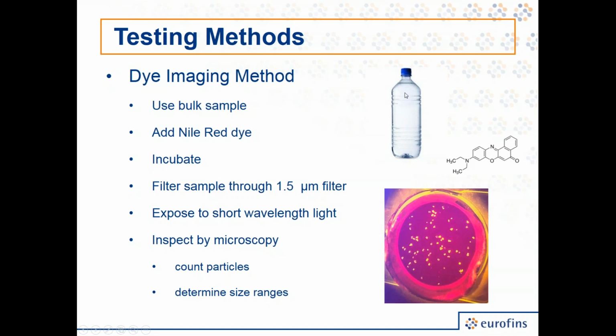In this case, it's a plastic bottled water. Sometimes samples are collected in glass jars, sometimes metal jars, and then that's sent to our laboratory for testing. What we do is, working on the entire bulk sample, we'll add a special dye called Nile red dye, shown here. This dye is very lipophilic, and it tends to adsorb and absorb into plastics quite readily. And it's pretty good, actually, at being absorbed to plastics, preferentially over other types of materials.